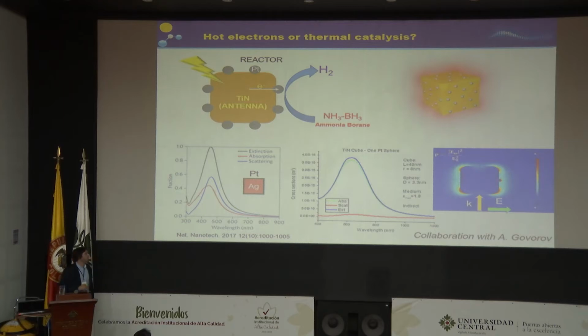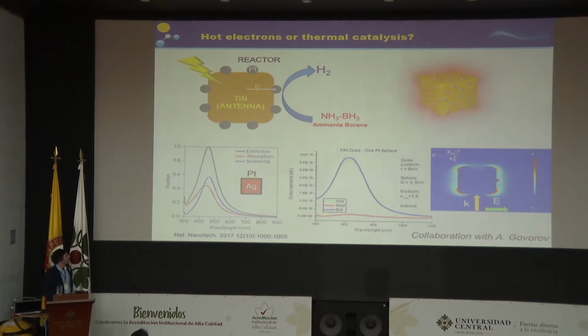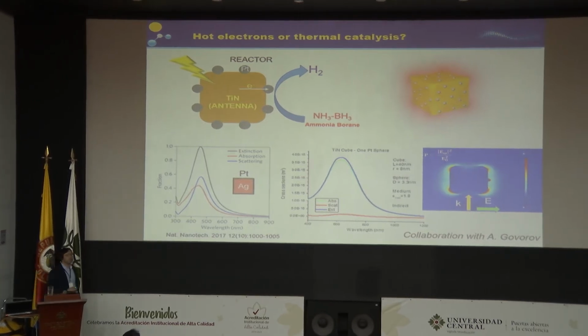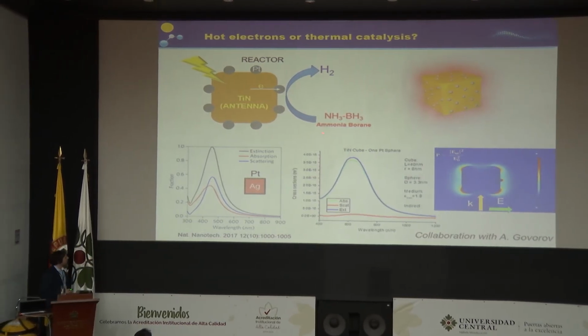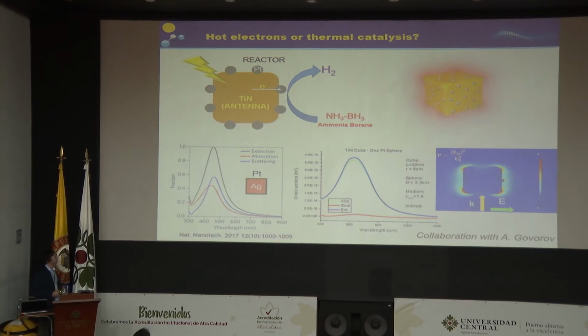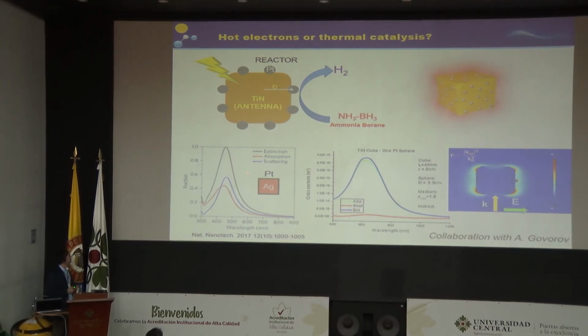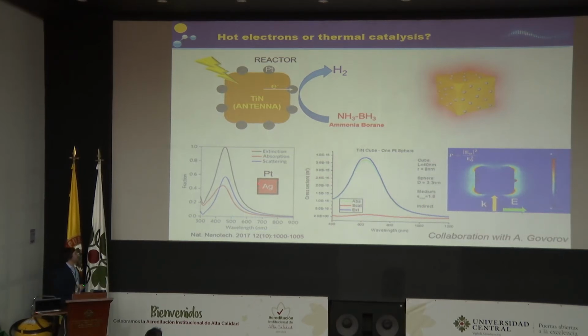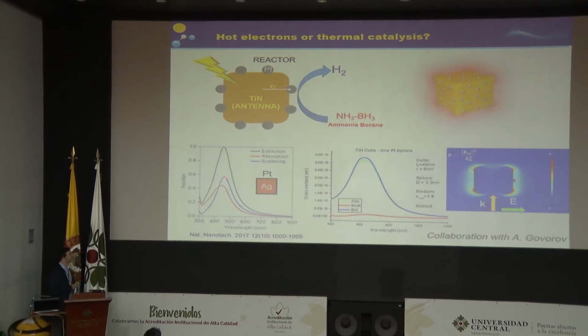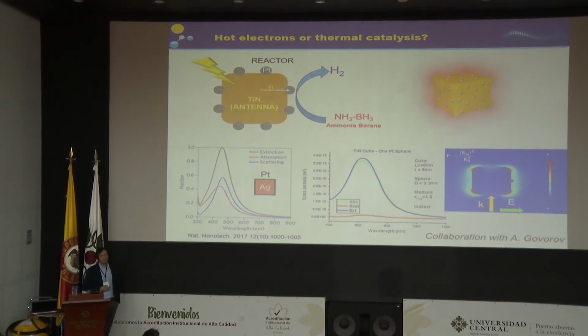What we studied right now, again in collaboration with Sasha Govorov, and we're just finishing writing the paper, is the use of titanium nitride with platinum for this catalysis. As you can see from our simulation, it's interesting to compare the properties of, for example, silver and platinum hybrids. In the silver we always have quite a big amount of scattered light, which scatters back from the surface of this material.